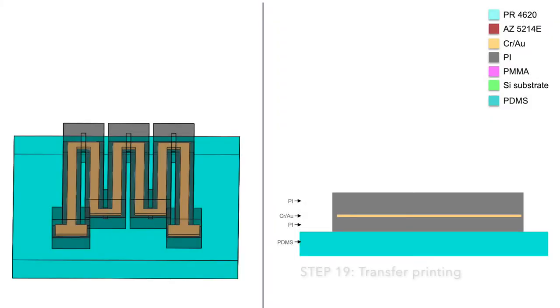We use a two-step transfer printing process to mount our device onto the PDMS substrate. In the first transfer step, we apply even pressure across the surface of a thermal release cellulose tape to ensure full adhesion.